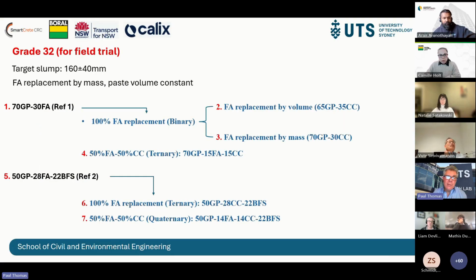In our program, we used the calcined clay as a replacement for fly ash, with a binary and a ternary blend. The binary blend is a 70-30 fly ash blend, replicated in the calcined clays. The ternary blends were blast furnace slag blends with fly ash, where again the fly ash is substituted with the calcined clay. We looked at two possibilities for replacing the fly ash.